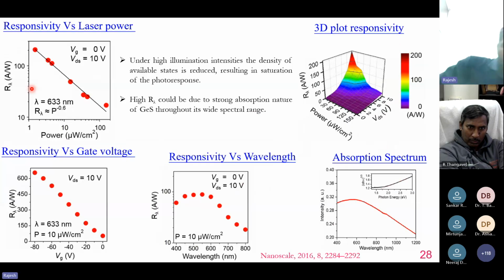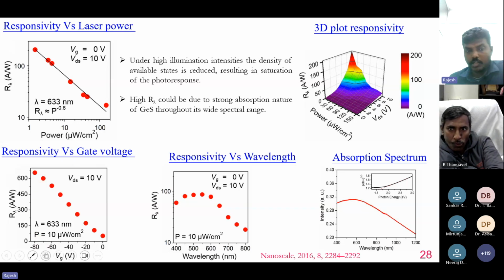So we extract almost double the responsivity of indium selenide, and we also improve this responsivity with the help of gate voltage. As I said previously, we can tune the number of charge carriers between the source and drain with the help of a gate. When we increase the negative gate voltage, we can clearly observe an increase in the responsivity. It's because of the p-type nature. So we are getting high responsivity in the negative terminal.